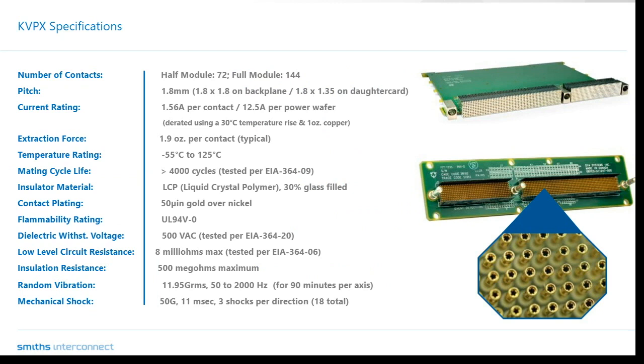So in today's discussion, we concentrate on vibration, shock, and temperature requirements, which we'll compare a little bit more in the following slides. However, shown as such, including some of the other general specifications of the KVPX connector system for your reference. Some key benefits include the greater than 4,000 mating cycle life, extraction forces of 1.9 ounces per contact. If you add that up, it essentially equals 274 ounces, or just 17 pounds for 144 contacts in our full width modules. Also, the industry accepted 50 microinches of gold is key to ensure our contacts endure in these harshest environments.